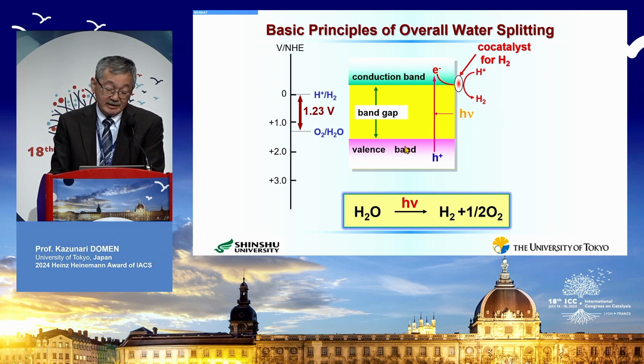On the other hand, the valence band maximum is located more positive than this oxygen evolution potential. Again, these photo-excited holes are able to oxidize water molecules or hydroxide anions into O2 molecules. In this case, I didn't show any co-catalyst. Actually, in many oxide-type photocatalysts, the surface of the photocatalyst itself works as an O2 evolution site.